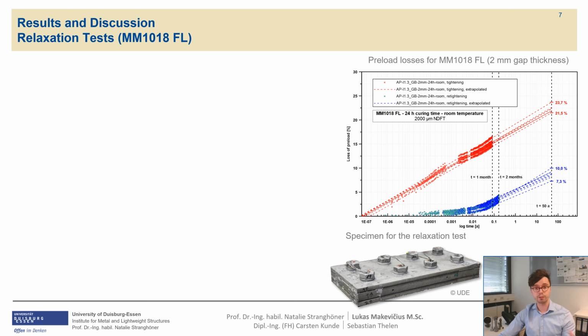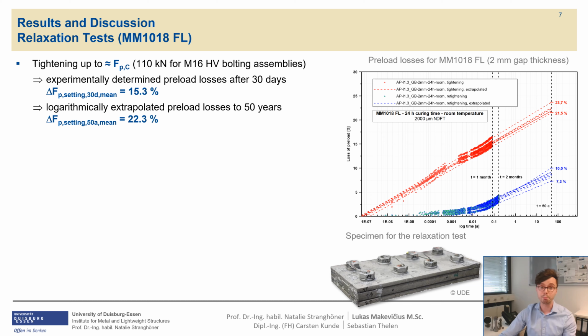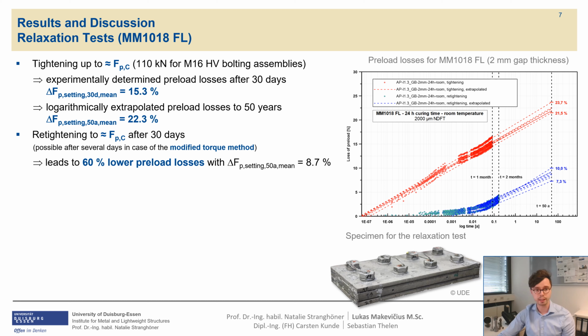In terms of the first relaxation test, the tightening was carried out up to the minimum nominal preload value F_p,C of around 110 kilonewtons for M16 HV bolting assemblies. The resulting preload losses were then measured for 30 days and extrapolated to the intended service life of 50 years, as can be seen in the diagram on the right. The mean preload losses after 30 days and 50 years averaged to 15.3% and 22.3% respectively. For the next step, the same specimens were retightened to the same preload level of F_p,C, which resulted in about 60% lower preload losses after the extrapolation to 50 years, of around 9%.